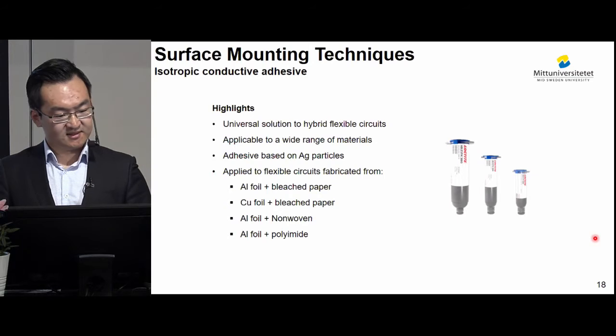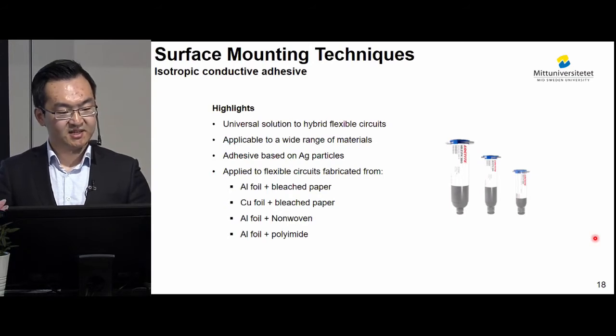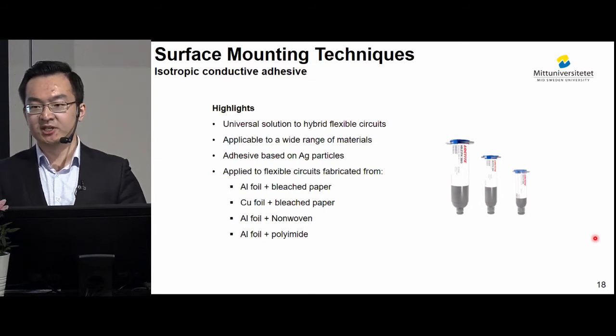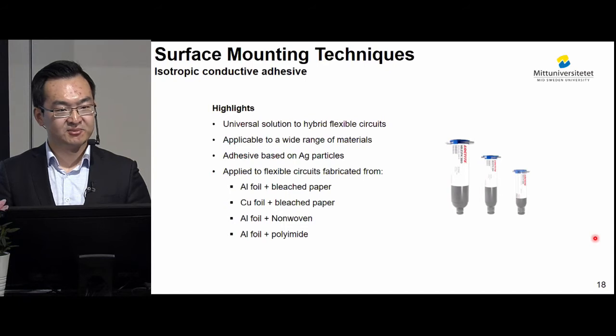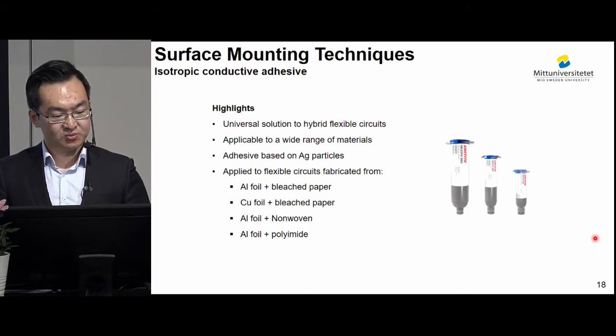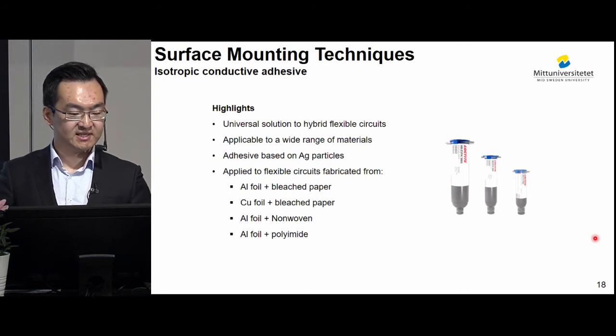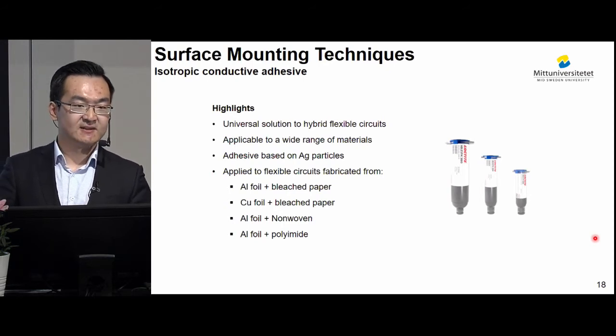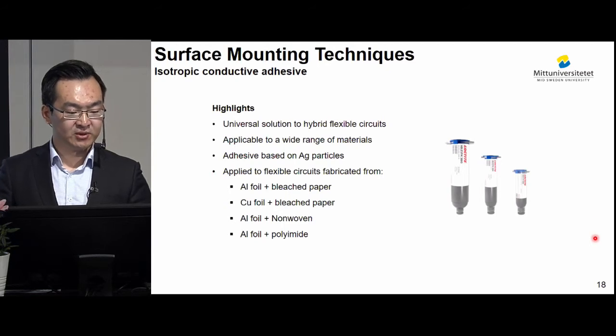We developed this because we think it is a universal solution to hybrid flexible circuits because it has a milder curing condition than low temperature solder paste. And because of that, it is applicable to a wide range of materials. In this work, we used an adhesive that's based on silver particles, and we applied this technique to the following 4 types of flexible circuits.